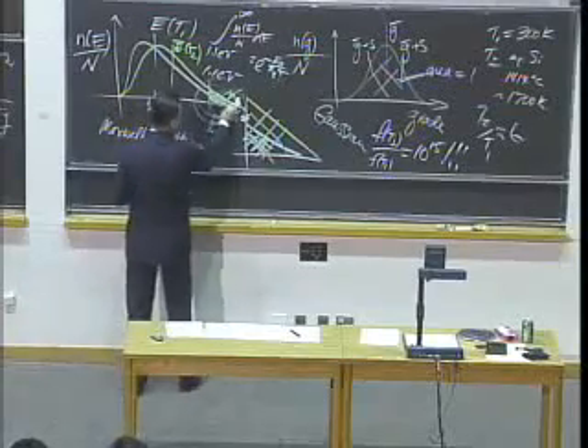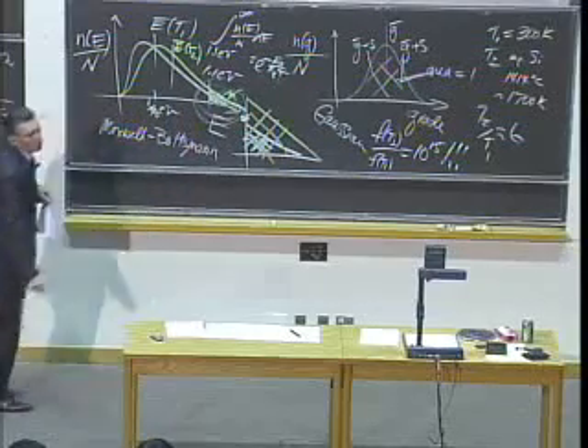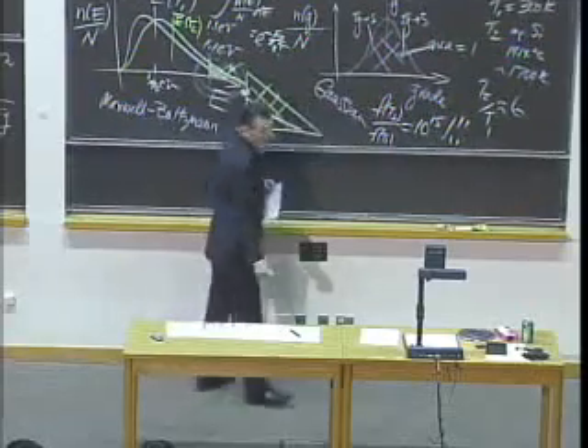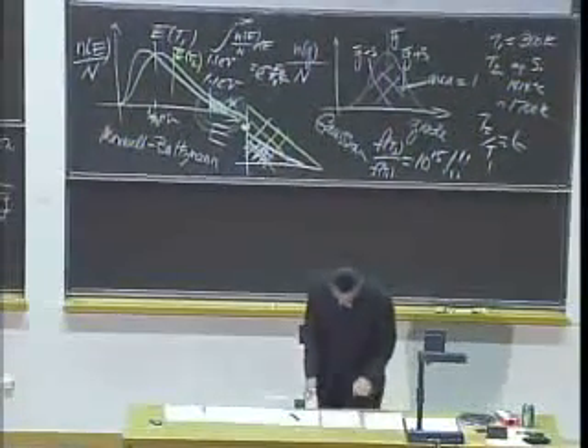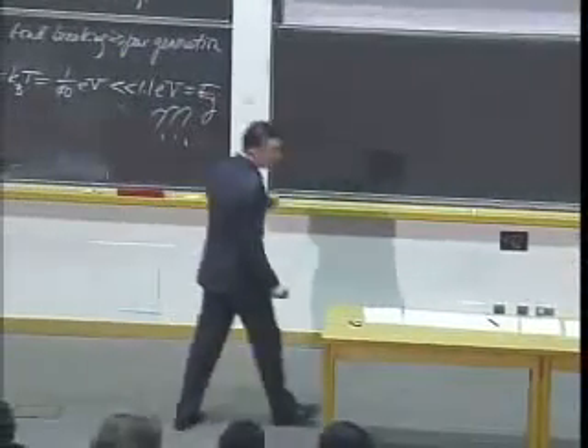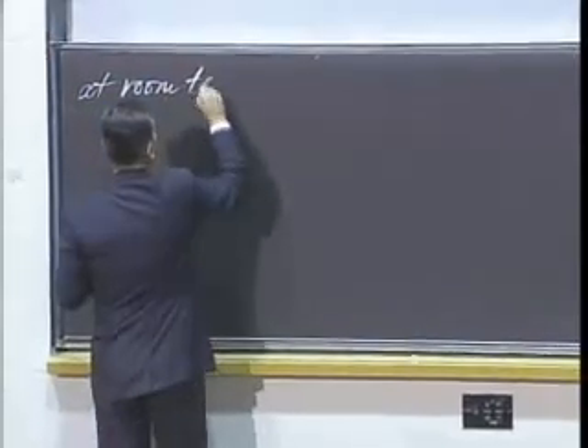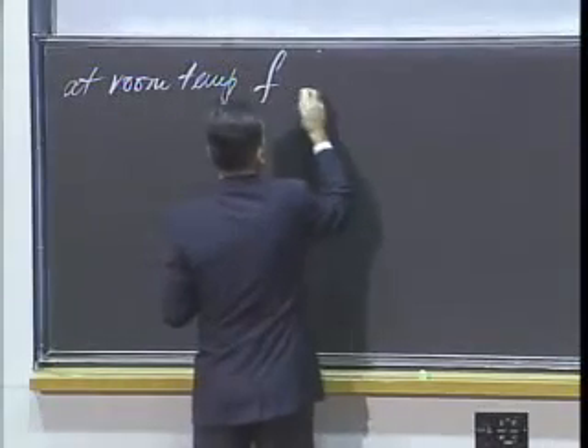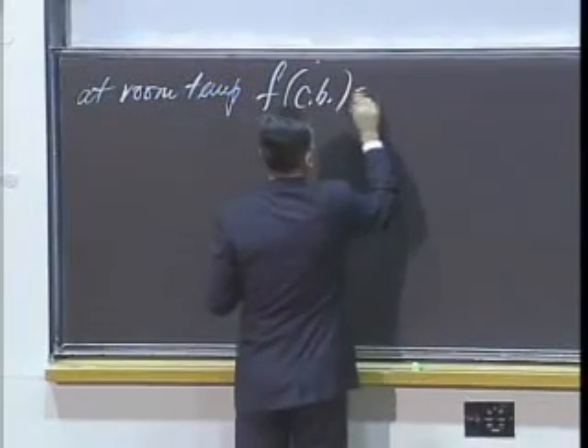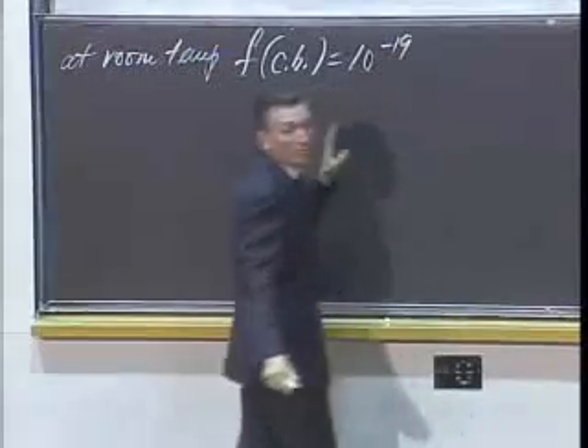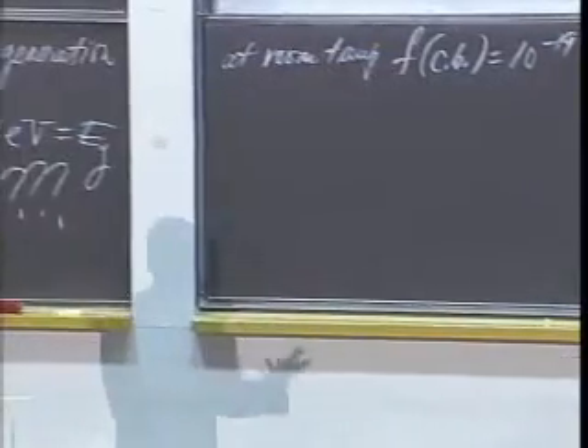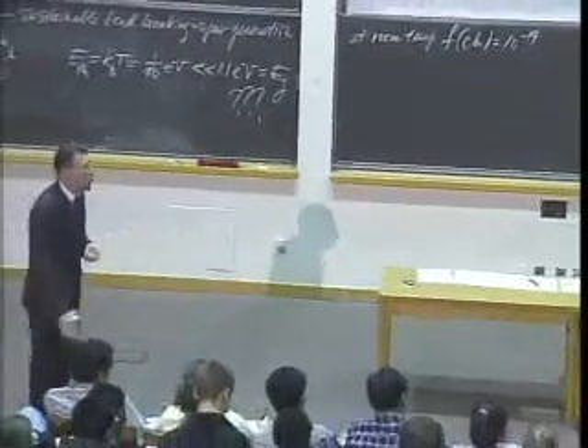So changing temperature changes the excitation population through the shift in the high end of the curve. And it's only through that that we end up seeing decent levels of population in the conduction band. Actually the number at room temperature is vanishingly small. At room temperature, the fraction in the conduction band is about 10 to the minus 19. There's so few of them you can give each of them a name. So there's almost no conduction. Silicon at room temperature is an insulator.